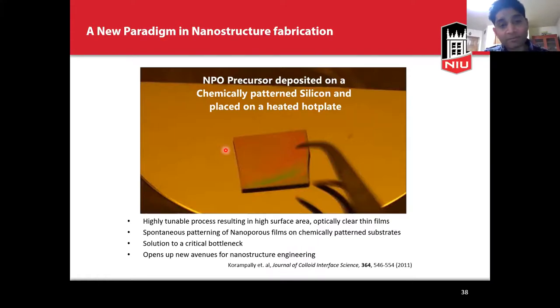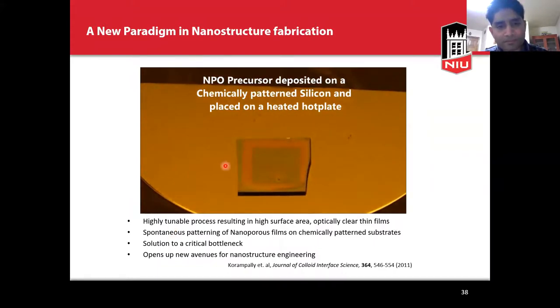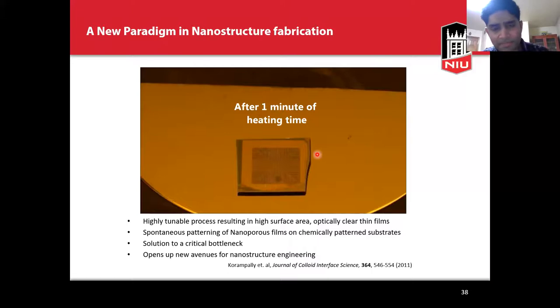Now, you cannot see the nanoparticles themselves, but you can see the macroscopic effect of that, because when I do this, as you can see here, in this particular video, it started out as a homogeneous film. However, the moment I place it on the hot plate, the nanoparticles that were present in these white regions formed a film with completely different refractive indices. And that's why you can actually see them as white. The optical properties are different. The way they interact with light is different. That's why you see a different color. On the other hand, you have these patterned regions here where the particles are assembled differently. They are more tightly packed in these dark regions. And that's why the optical properties are different and manifest as a different color. So we can actually see that.